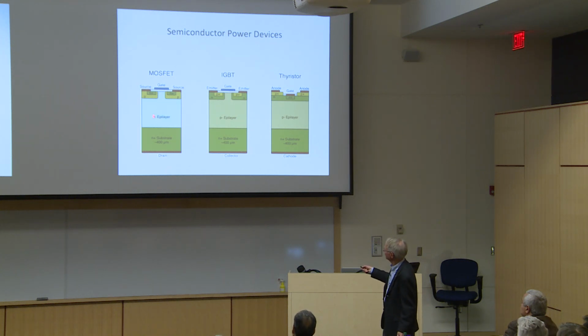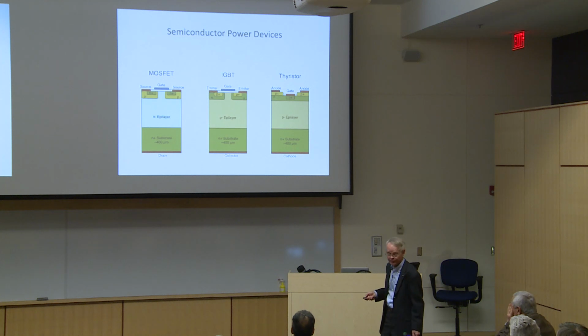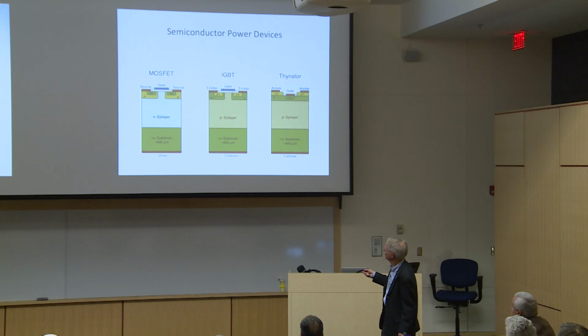You order it with an epitaxial layer, a thick, lightly doped N-type layer. This is all single crystal, perfect crystalline, and you get this from the vendor. And then to do the fabrication, at the very top, we will implant a P-type dopant to form these P layers. We'll implant a heavier N-type dopant to form these layers. We'll grow a thermal oxide here. We'll open windows and put these metal contacts on it and alloy those to make electrical contacts. We'll put a polysilicon gate on top.